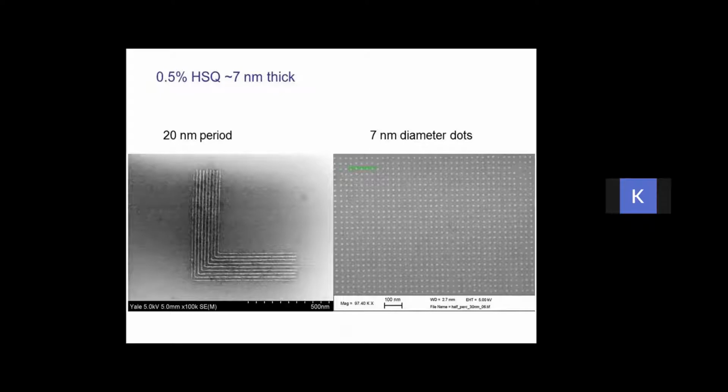For that, the resist thickness has to be very low, and that is not possible in most cases. So we can safely say you can make patterns of around 50 to 100 nanometer in most cases for your applications. If you have to go for 20, 30 nanometer, then you have to keep in mind that the resist thickness should not be much.